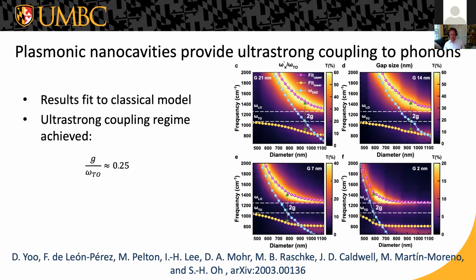And again, not to go into the details of the fitting and the model that were used, but a classical model reproduces, again, the same results as a fully quantum mechanical ultra-strong coupling model in this case. And the anti-crossing curves give you a coupling strength, which is about 25% of the transverse optical phonon frequency itself. So, ultra-strong coupling is, I think, generally held to occur somewhere about 10% of the transition frequency. So we were pretty well into the ultra-strong coupling regime here. I should say here we've moved into the infrared wavelength regime. Right?